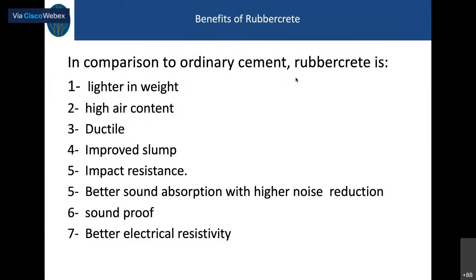The inclusion of crumb rubber in concrete leads to many benefits. The concrete becomes lighter in weight, with high air content, more ductile, improved slump and impact resistance. When we talked just now about column-beam joints under cyclic load, this is a very good material for that area. It also gives better sound absorption with higher noise reduction, soundproofing, and better electrical resistivity.